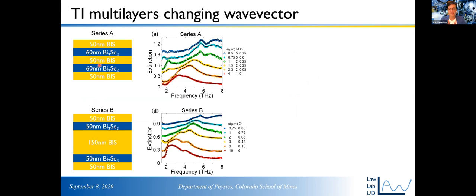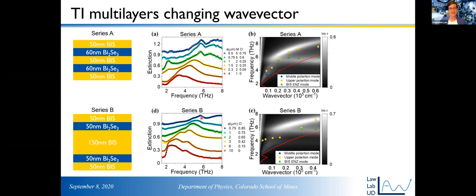We fabricated them into stripes again, changed the stripe width to change the wave vector. And these are what the extinction curves look like for these different stripe widths, right? So each of these is a different wave vector, and you can see all sorts of modes in here. The black lines are the multiple Fano resonance fitting that my student did. He then also created a whole T-matrix model, which is what you're seeing in the color plot, to actually model what we expect from these samples.